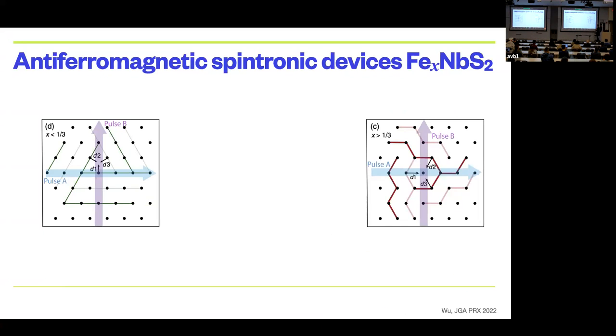That's what the domain walls look like. So one of those domains would be just stripy order on the left-hand side. And then there are 3 configurations of the domain walls form. And that's what a domain wall would look like. But these are magnetic domain walls. They're also structural domain walls. There's an electronic anisotropy with each of these domains. There has to be a structural response.